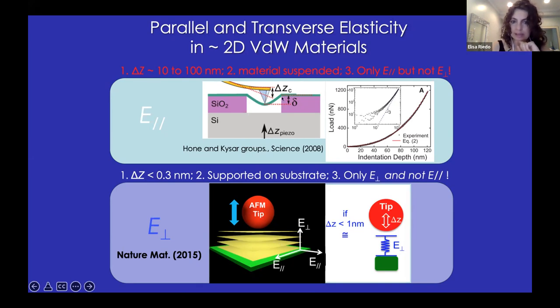when you bend a graphene, or another 2D film, on top of a membrane, your indentation depths are of the order of 100 nanometers, which is something, let's say, relatively easy to measure with an atomic force microscope. On the other hand, if you have a film of, say, three layers or two layers on a rigid substrate, and you want to indent and measure the elasticity between the layers of the film, then your indentation needs to be very small.